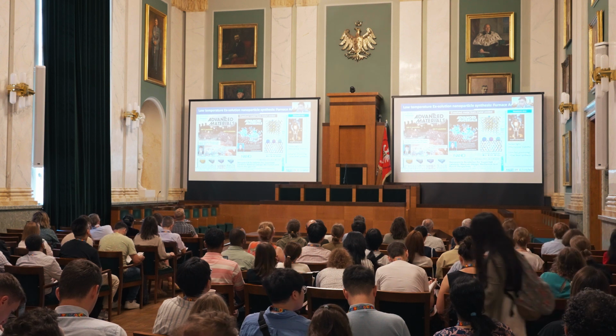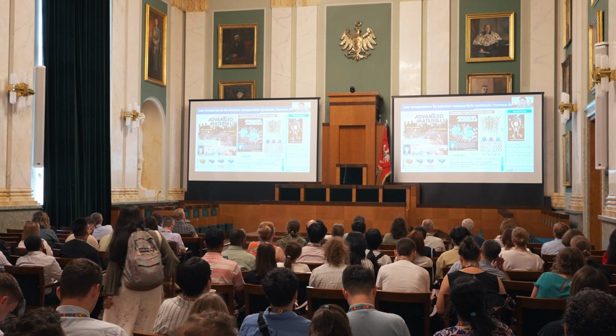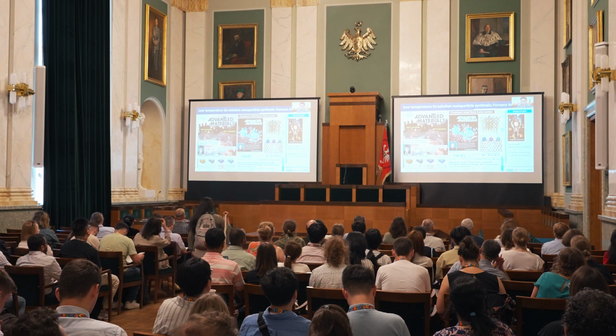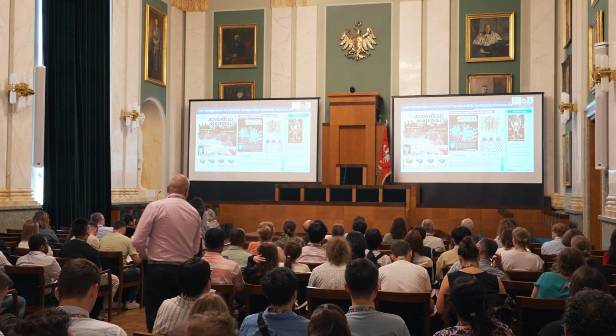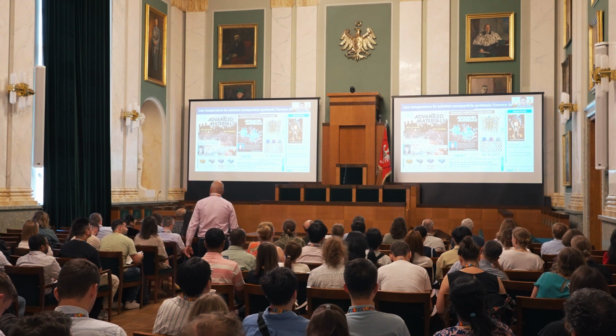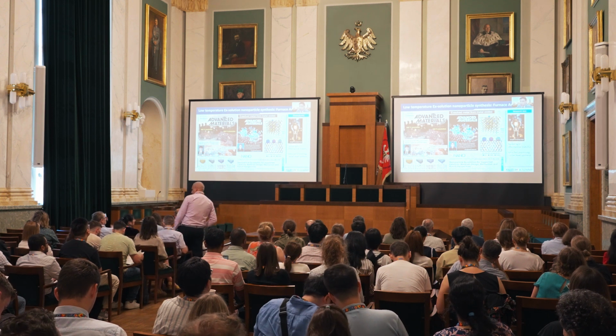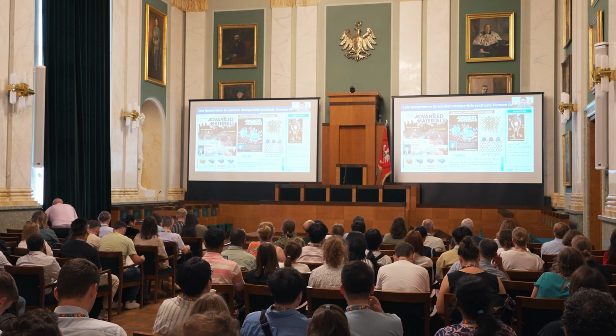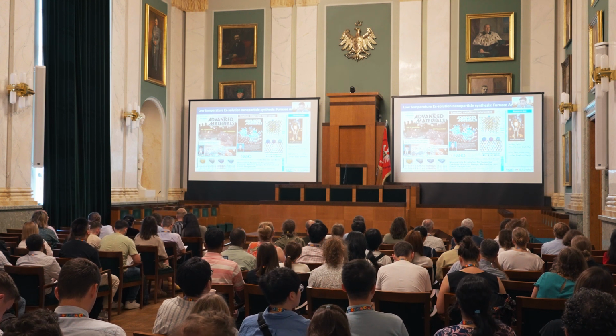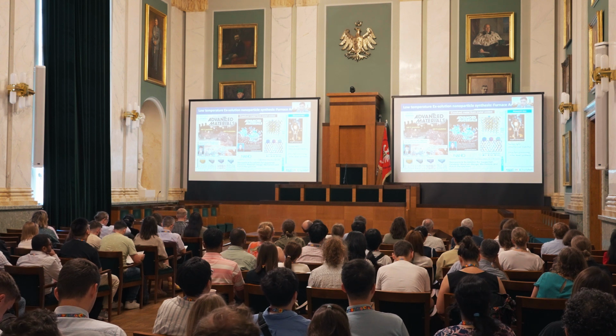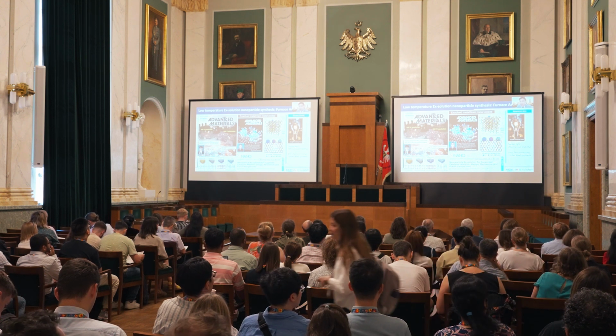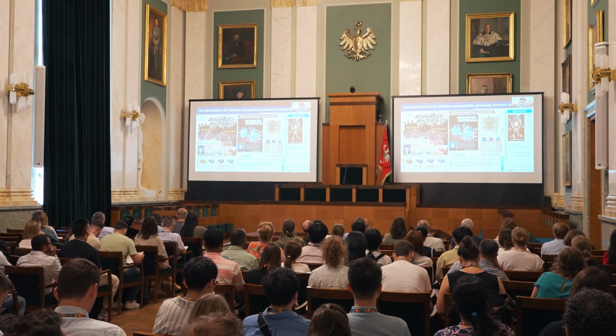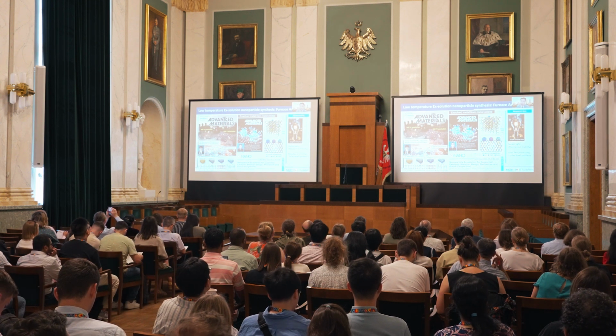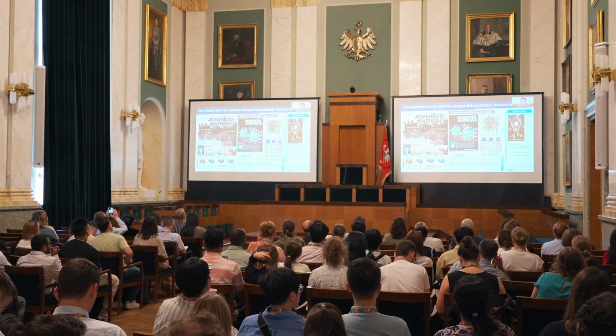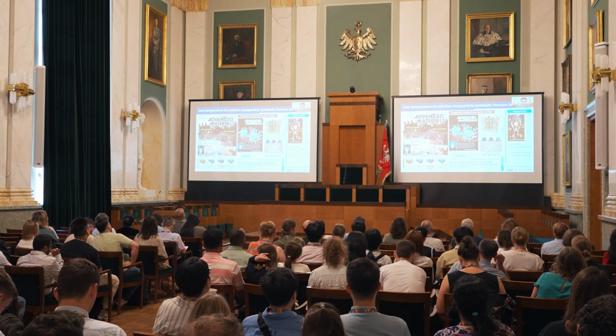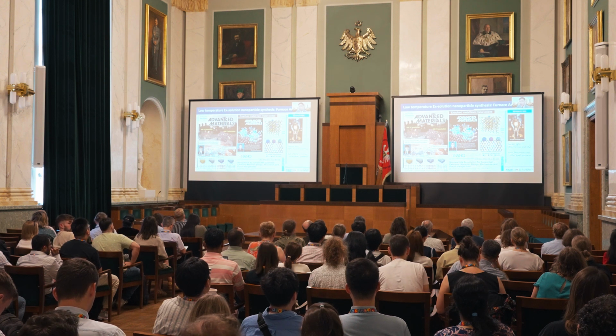Then we also use ZIF8. By annealing this ZIF8 in an air atmosphere, we can synthesize porous zinc oxide. After incorporation of a foreign element, with additional annealing in a reducing atmosphere, we can also see this exsolution. Single-element particles, and also bi-elemental, bimetallic particles, can be synthesized using this ZIF8-templated zinc oxide material. But the temperature, 300 to 500 degrees C, is much reduced compared to the perovskite oxide, though still high.